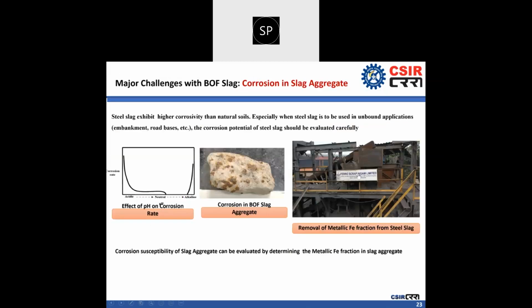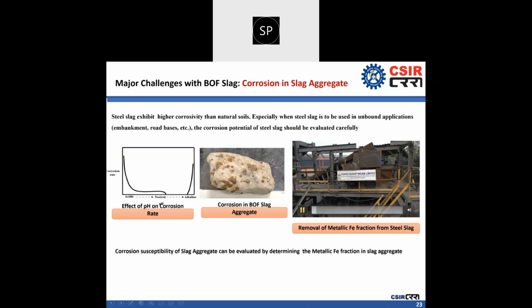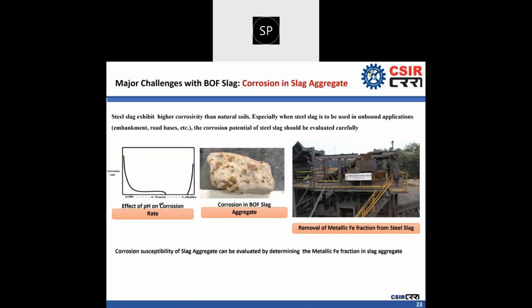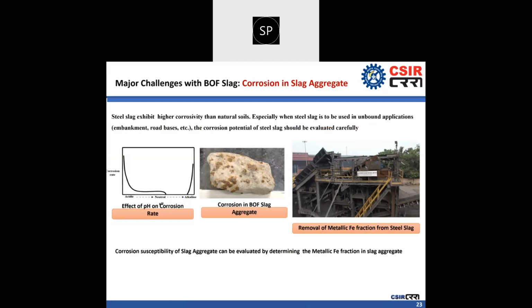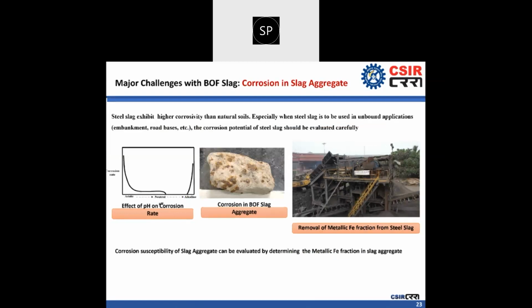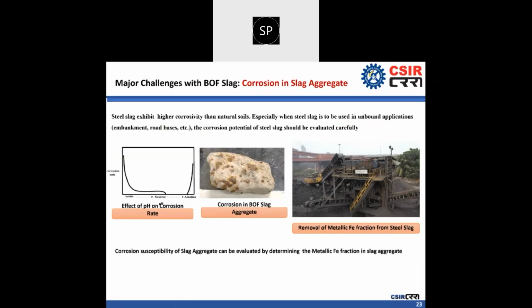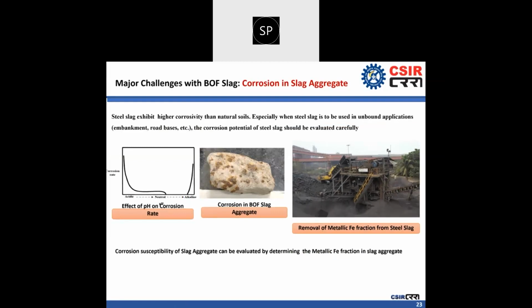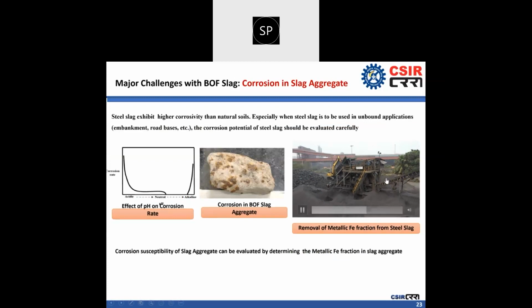The fourth one is the high metallic content. If the slag aggregate contains high metallic iron, then this metallic iron will corrode with time, and the slag aggregate will have a corrosive appearance after 1 or 2 years. So before its utilization, the slag aggregate should be subjected to magnetic separation in order to remove the metallic iron and trapped metallic iron from the steel slag. CSIR CRRI has customized this process to bring the metallic iron content down to less than 4%. Whatever metallic iron is recovered from the slag is recycled in the steel plant to produce steel. This is a glimpse of the metallic iron removal process which you can see in this slide.